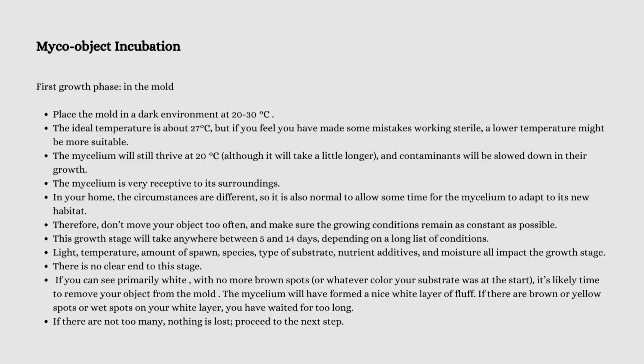So even at 20 degrees, your mycelium will grow and will thrive, but it will be a much slower process. And in that slower time frame of the mycelium taking advantage of its food source, something else might take advantage, which we call contamination or just other organisms. So this may slow down its growth even more, or you may have to toss what you're working with.